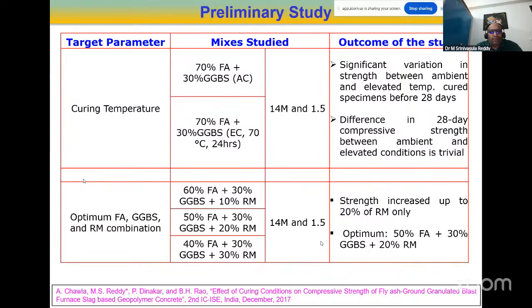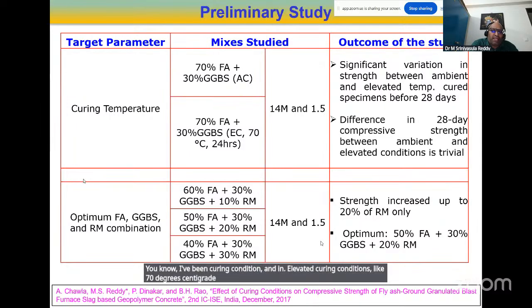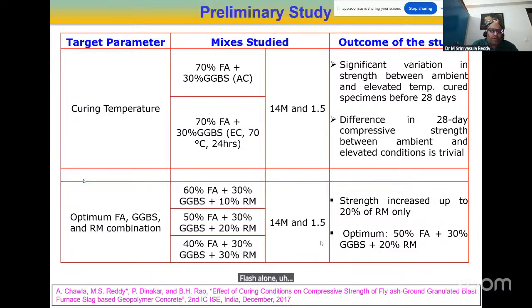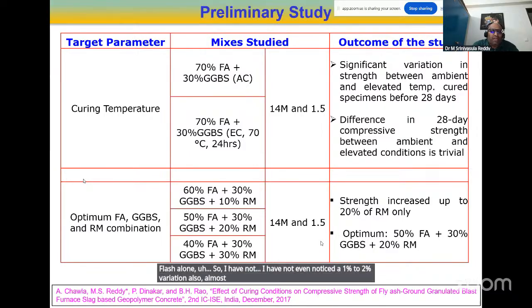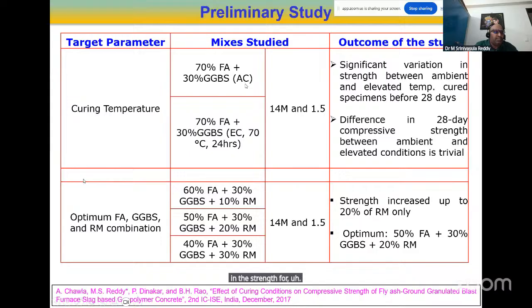And one advantage with this fly ash GGBS combination is that I tried casting and curing cubes both in ambient curing condition and in elevated curing conditions, like 70 degrees centigrade, which we generally use for fly ash alone geopolymer concrete. I have not even noticed 1 to 2% variation. We can say less than 1% difference between the strengths for ambient curing condition and for elevated curing condition for 24 hours. So you can discard elevated curing if you go with fly ash and GGBS.